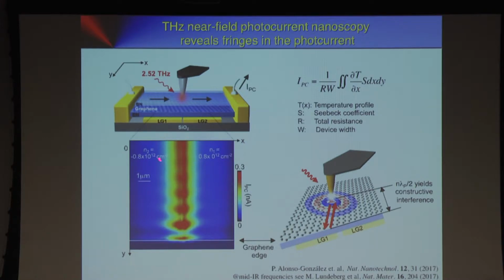Now, the fascinating thing here is that we scanned this device, and here we see the active area where all the photocurrent is generated. It's an area of about 1 micrometer. We shine a spot size of 100 micrometer, and we get this high photocurrent generation, and we see that we get a resolution in the range of 50 to 100 nanometer with this technique.